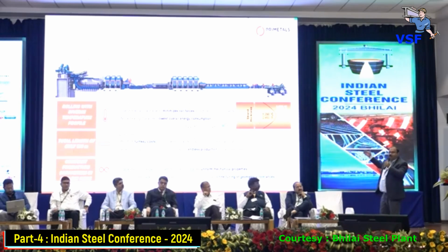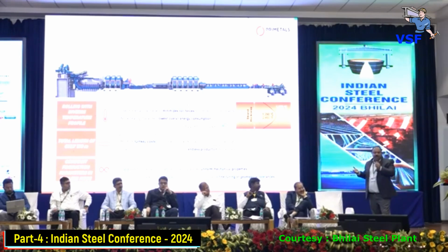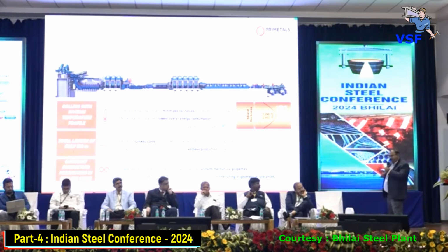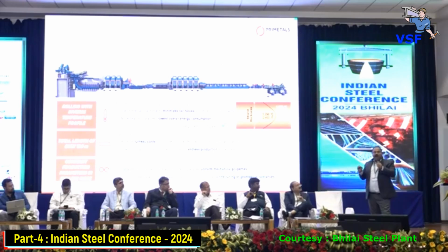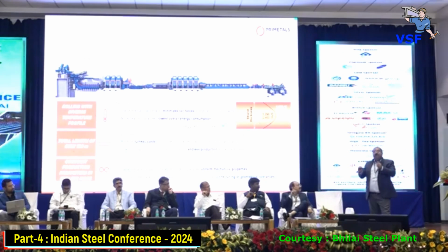And when you are having the inverse temperature, when you are having reduction, throughout the volume you are getting the transformations. So whatever the product you are having, it is not only the surface, it is basically reducing and changing throughout the cross section. This is the beauty of this product. And we are going for a continuous mode. Since we are going for a continuous mode, this is the only hot strip mill which is producing below 1 mm thickness HR coil in stable production commercially.